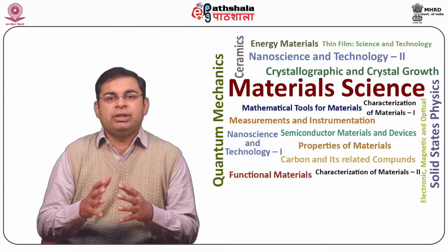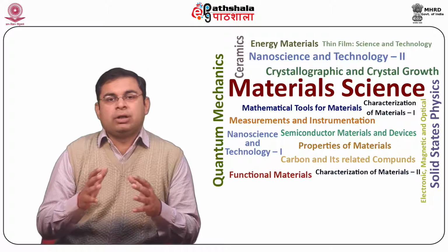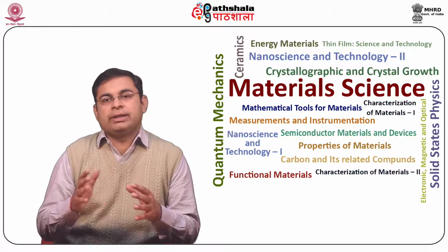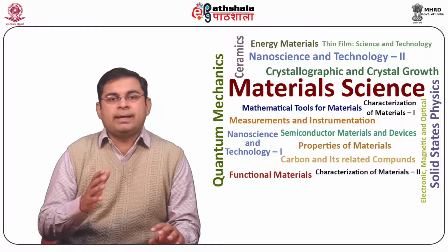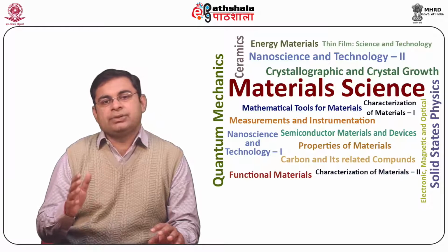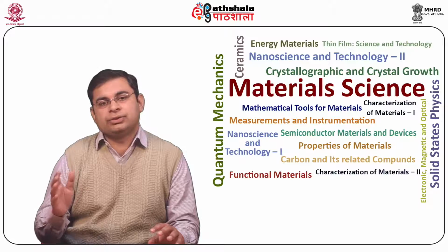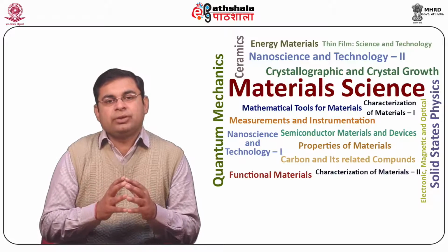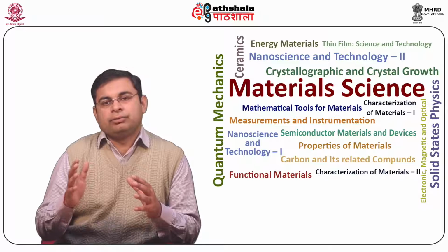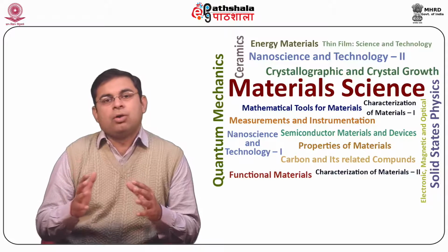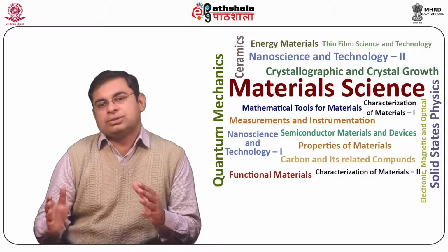While considering a free electron quantum gas, the obtained Hall coefficient is 1/nq, same as the classical case, along with the nil magnetoresistance. The difference in results is more evident when a more realistic model for solid material is considered, for example, crystals.